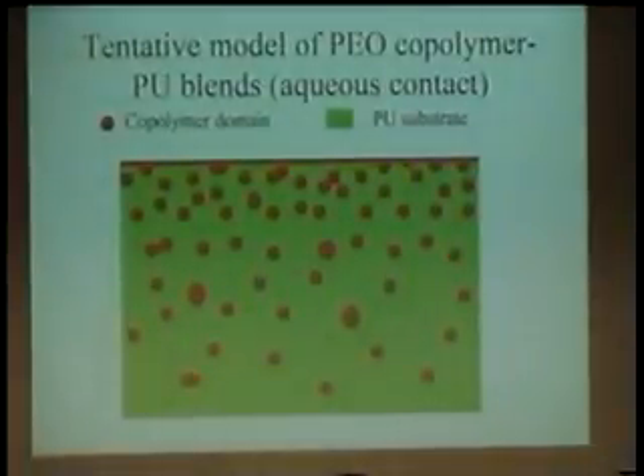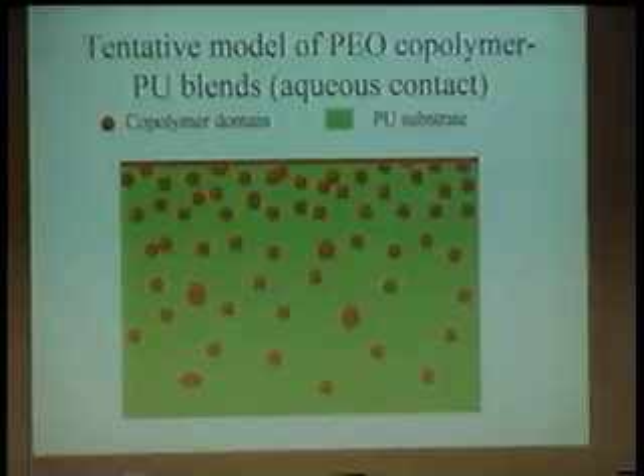And so, as I say, this is ongoing work. We yet have to come up with a satisfactory structure for this interface. But here's one idea. This would be like a cross-section cut down into the material now. We do have this domain structure, and we have to deal with that. We have to deal with the fact that if it's like this on the surface, then there's all kinds of matrix surface which does not have PU on it, which ought to absorb a lot of protein based on our data.